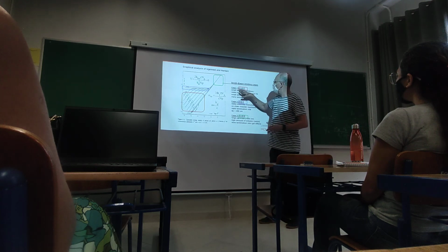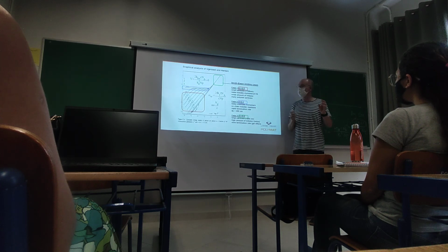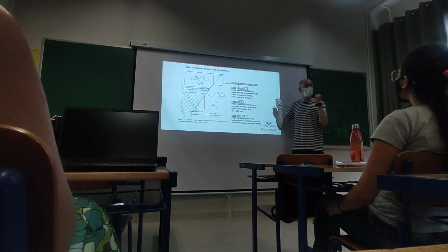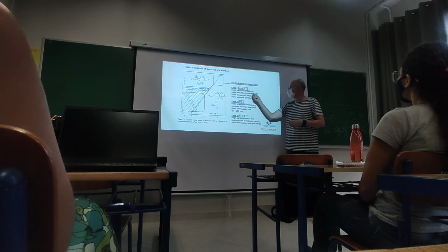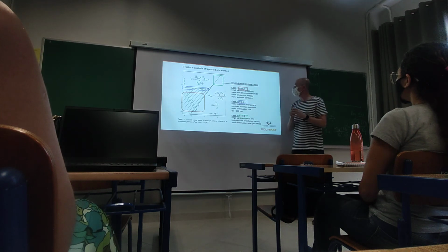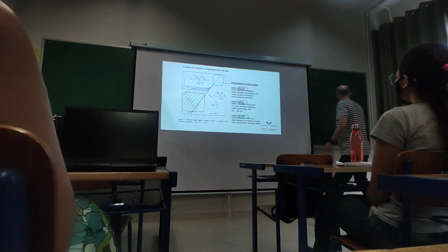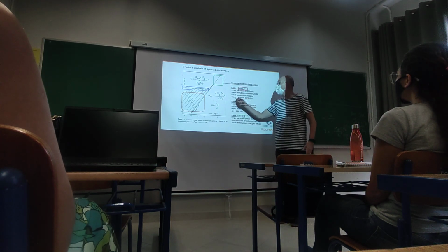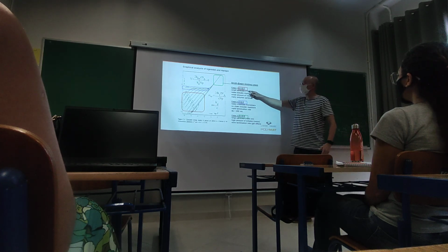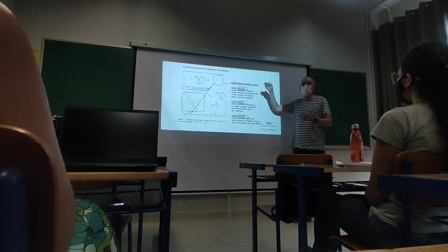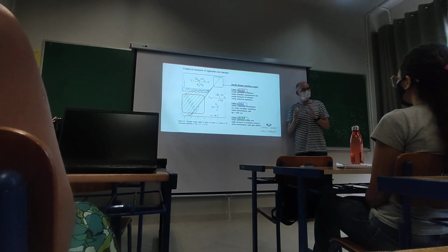Okay? So, n bar below 0.5. We need very small particles, below 100 nanometers, and very water-soluble monomers because we need desorption. So to have desorption, we need small particles to have fast diffusion, and water-soluble monomers that would like to go out, and a small amount of initiator. We are in this area, so this should be small, or k_p very high. But this is related to the number of particles. If the size of the particles is small, we will have a large number of particles.